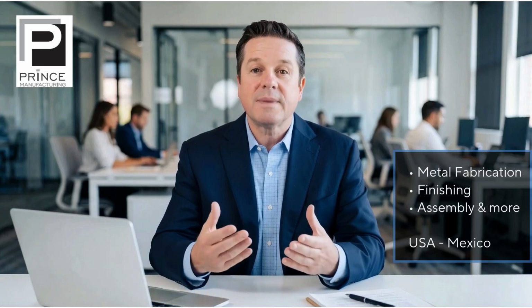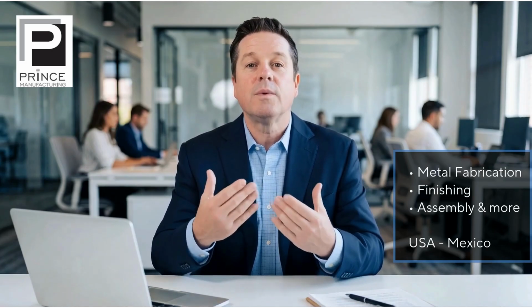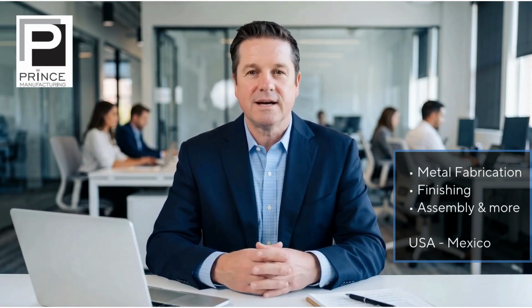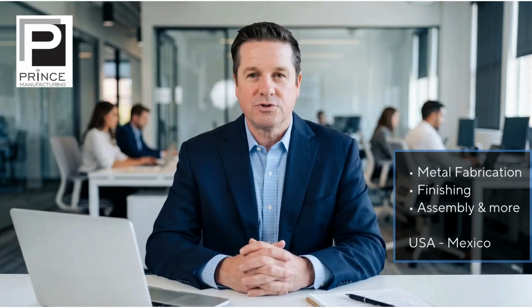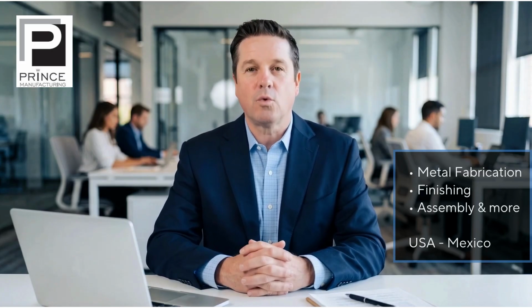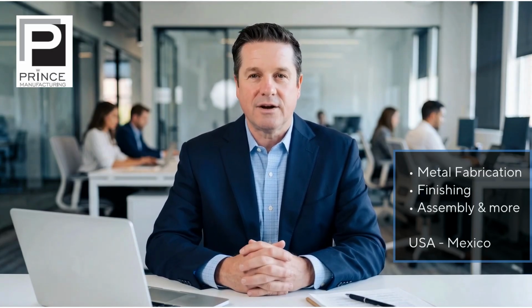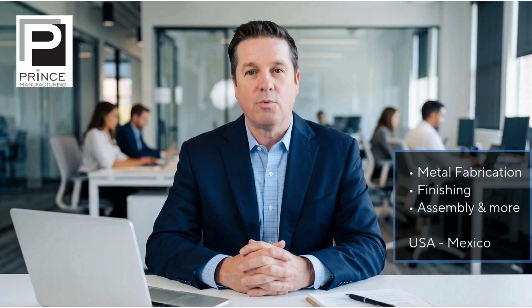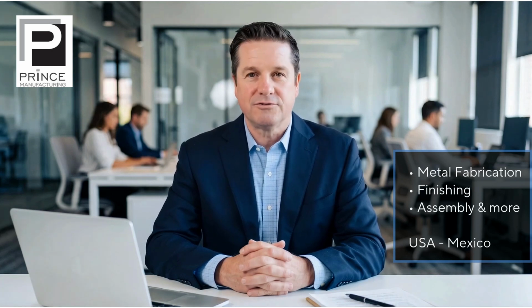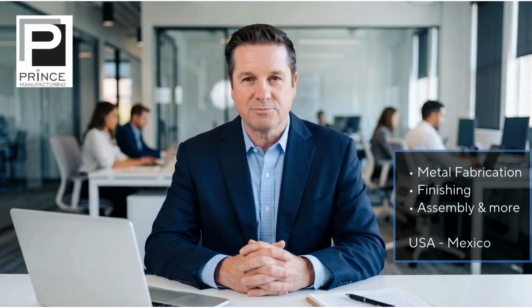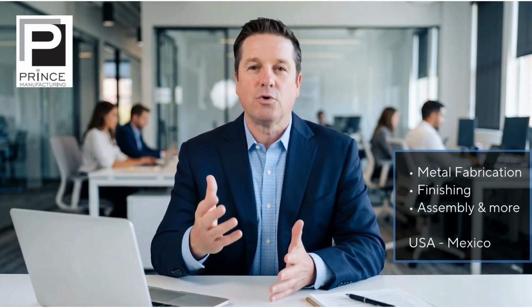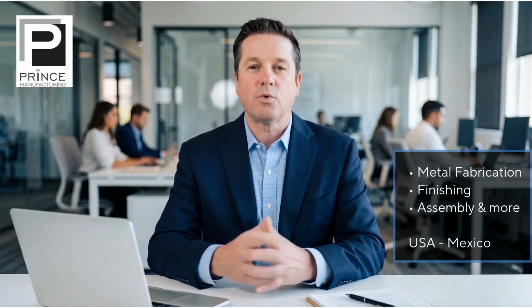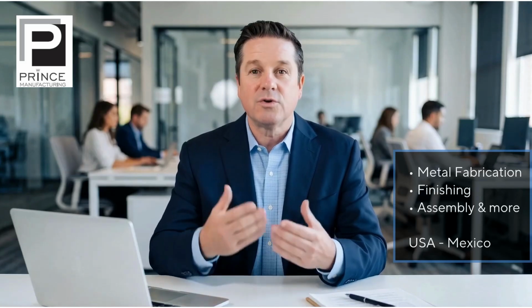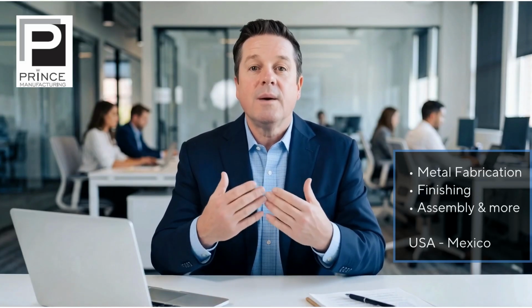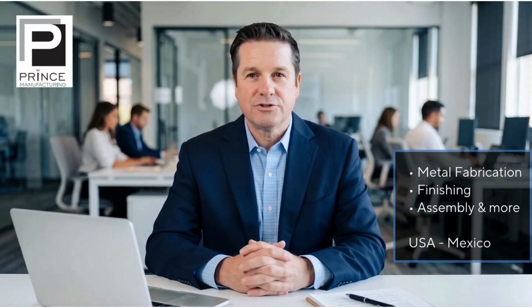Let us summarize the major process families. Consider metal plating when you need a relatively thin metallic deposit, sacrificial corrosion protection, conductivity, solderability, wear properties, or another metallic function. It can also be appropriate when dimensional control is important or when the drawing requires a specific plated finish. Consider fluidized-bed coating when you need a heavy, continuous polymer coating with impact, abrasion, chemical, or electrical insulating properties, and the part geometry can accommodate the process and additional thickness.